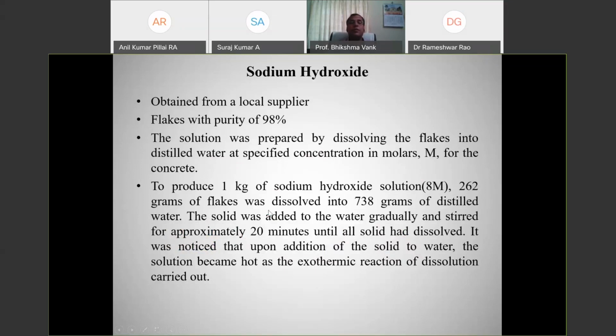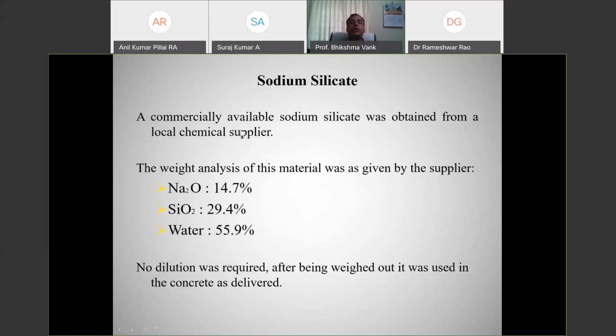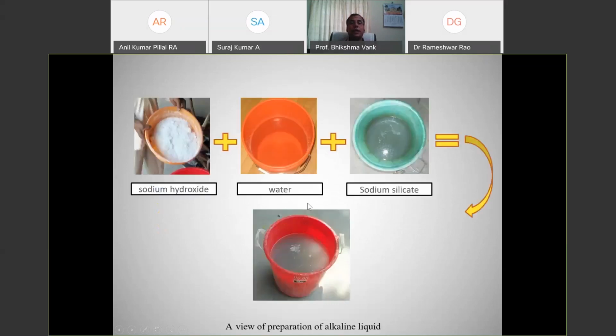This is the procedure of the mix design. We have done several trials, and based on the trials we got the compressive strength value. These are all the requirements of sodium silicate: Na2O 14.7%, SiO2 29.4%, water 55.9%. This is how the mix design has been taken, and this is very interesting. Sodium hydroxide, water and sodium silicate together will give you the alkaline liquid, and finally the view of the preparation of the alkaline liquid will be like this.